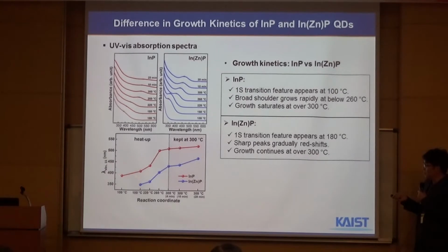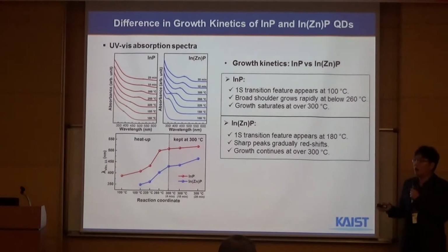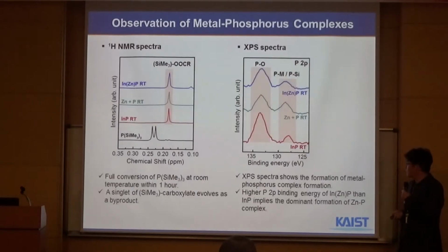You can see that the y-axis is the wavelength of the absorption. Typically, when the size is larger, the wavelength is in the longer range. So you can see from these two samples that by putting in zinc, you basically slow down the reaction. It's getting slower compared to the red dot, which is indium phosphide. The question, of course, is why we have slow growth of indium phosphide.